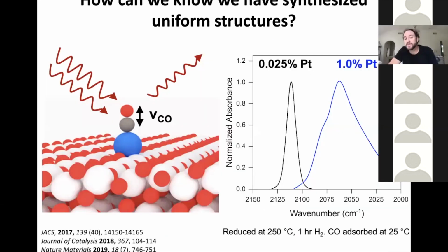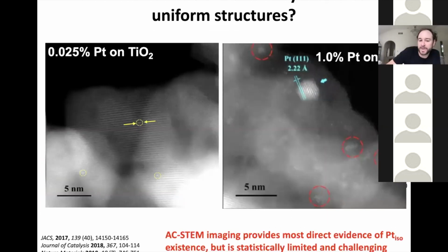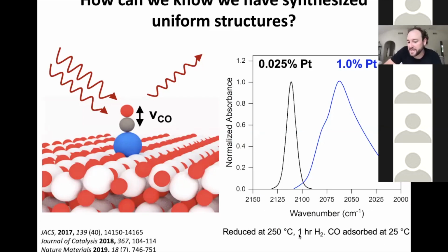So what we've been using a lot is infrared spectroscopy using probe molecules. We like this because probe molecules adsorb everywhere they can possibly adsorb, so you're making a statistically relevant measurement. You're probing all of the sites. So for example, if we took those 2 catalysts I showed you on the previous slide, we reduced them at 250 C in hydrogen, and then we adsorb CO at room temperature. One shows an extremely sharp stretch, and one shows a broad stretch.